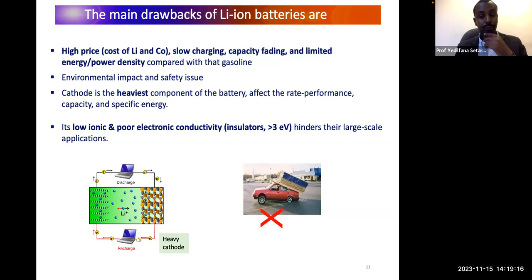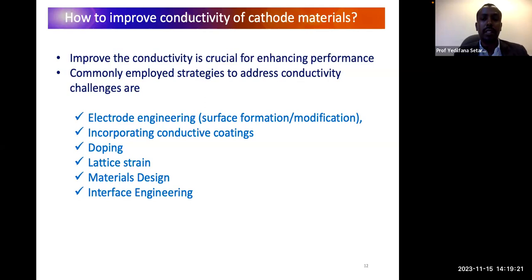So how to improve the conductivity of the cathode materials? Improving the conductivity in a battery is crucial for enhancing the performance of the battery. The commonly employed strategies to address the conductivity issues are electrode engineering. If the bulks are insulating, then we transform them into surfaces, and we can also modify the surface. Another strategy is incorporating conductive coatings on the surface, and adding some impurities which can enhance the conductivity of the bulk material, and also introducing lattice strain, just altering the geometry of the cathode, and that actually results in a positive change in the conductivity.